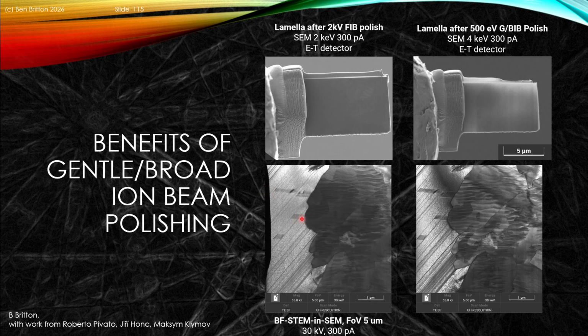And then post the broad ion beam method, so we did the 500 electron volt BIB method using the argon, and we see that we now get a significantly improved, much higher contrast in the features that are presented, and that's much more easy to interpret. So that's a nice aspect where we can combine the FIB with final polishing steps. Other final polishing steps could involve using an ex situ broad ion beam, or we could use things like flash polishing that are described in the literature.